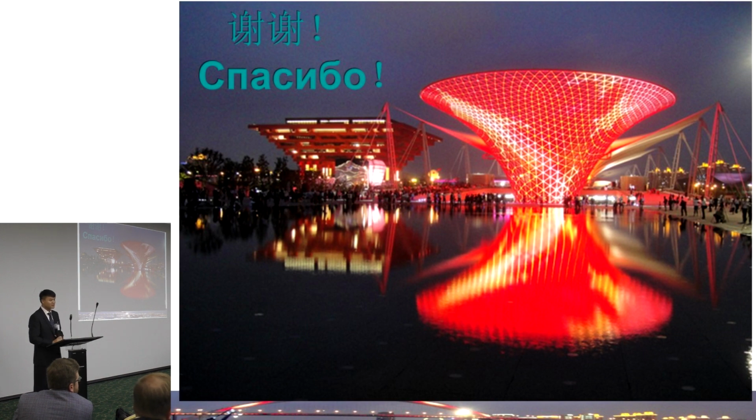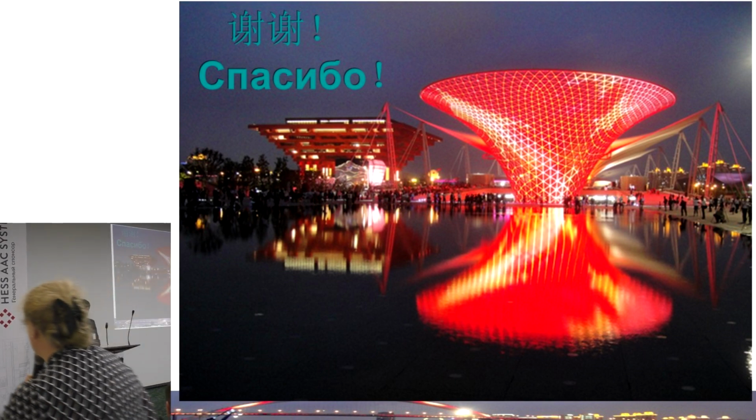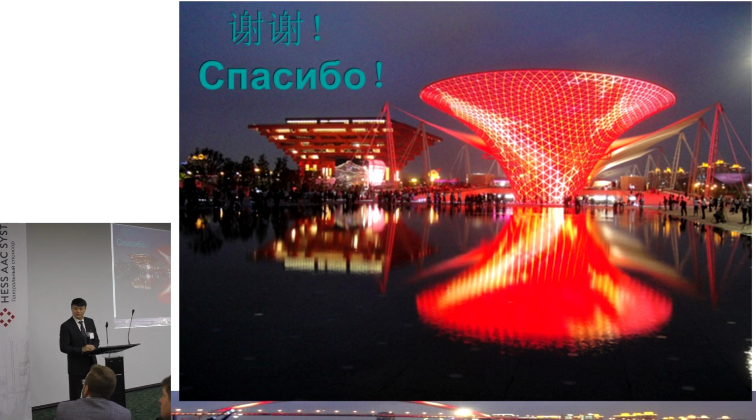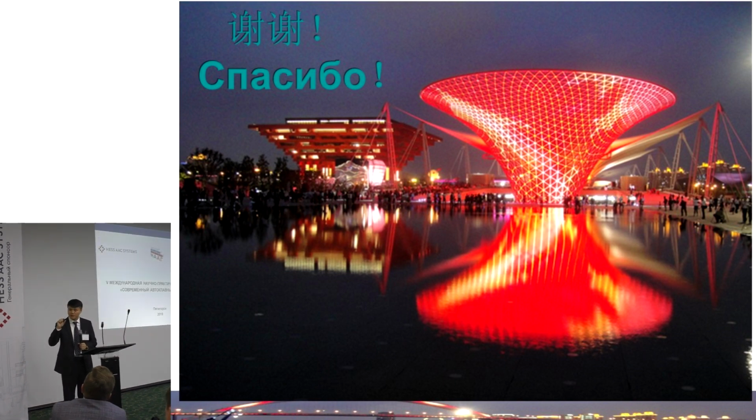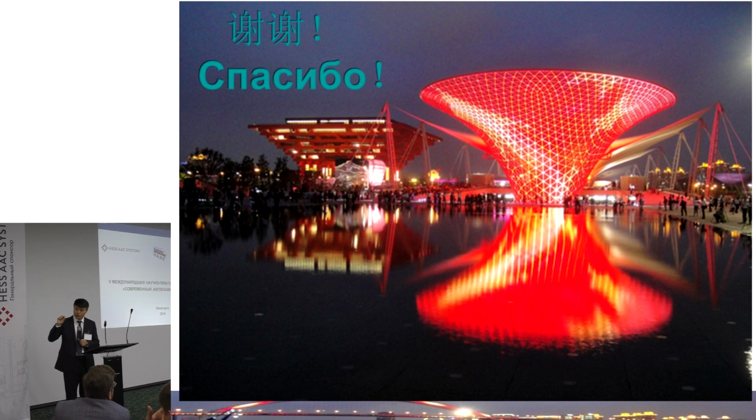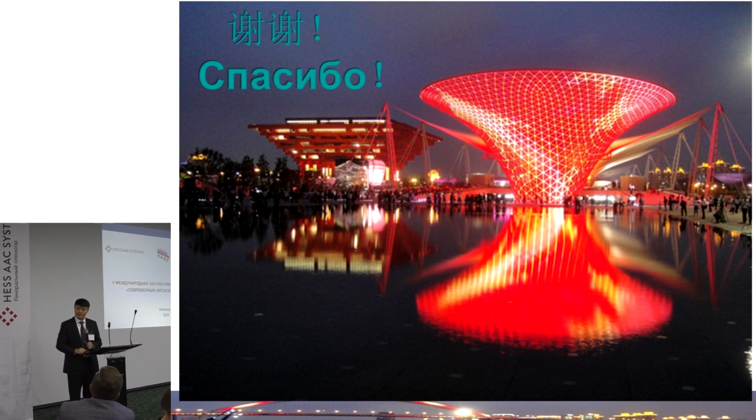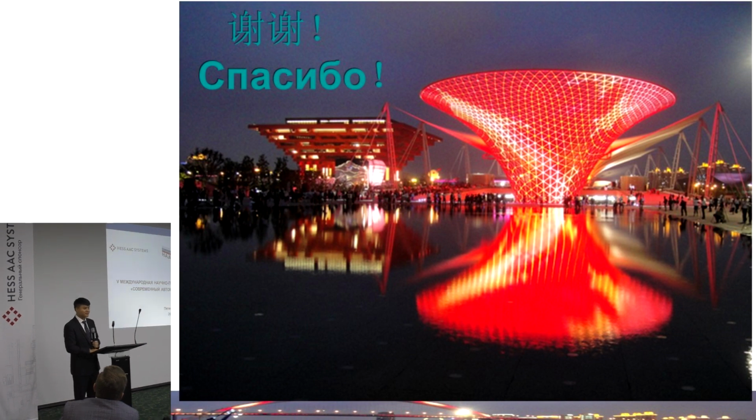Tell me, please, is the use of mortar with a thickness of 10 mm a matter of tradition, or what is it related to? Why 10 millimeters? The joint thickness is traditional. This is our traditional type of joint. When we use dry mortar, the modern joint is thinner, 2 to 3 millimeters.